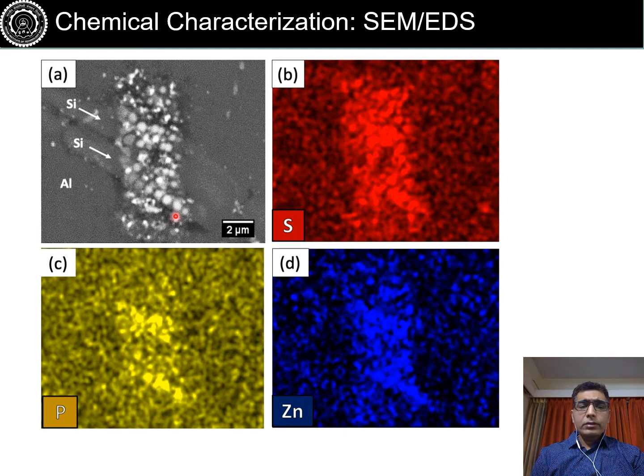We could also chemically characterize this film simply looking at the elements present, and we see that there is higher concentration of phosphorus and sulfur where film is forming on silicon. Of course, it's denser and thicker film, so that is expected.